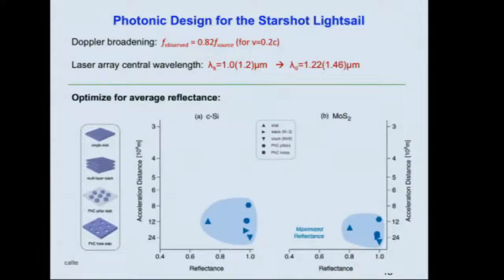And here's what we found. We found an array of solutions where the reflectance was close to 100%. And the good news is that for the two candidate materials we analyzed in detail, multilayer molybdenum disulfide, like the materials I showed you we made solar cells of on Tuesday, or thin films of crystalline silicon, there are many solutions. I have photonic crystals. I have slabs. I have stacks of materials that all work.